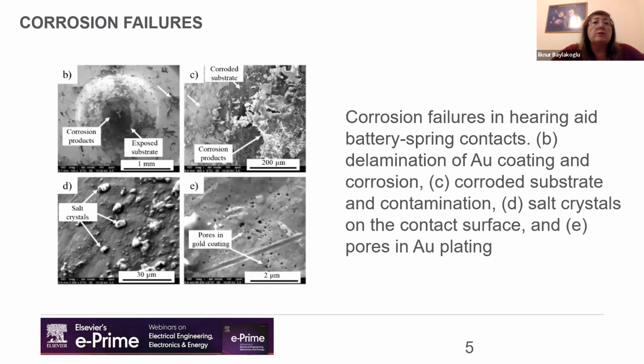There is another corrosion example on the hearing aid battery spring contacts. Actually, it is again a galvanic corrosion observed in the battery contact springs of hearing aid. Because the contact springs are made of nickel electroplating with gold finish, and these pores are found on the gold surface, which appear to be formed by corrosion resulting from salt dissolved in the water.